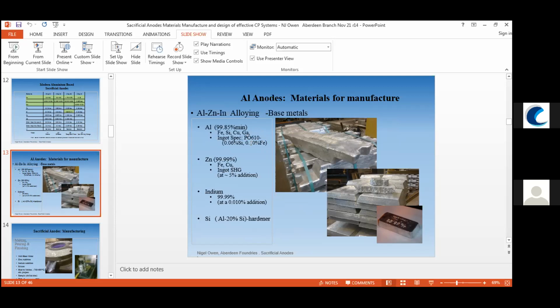We're buying aluminium of P0610 grade, as it's known, and this is a standard grade, and that nomenclature means that you are using 0.06 silicon, and 0.1 iron is the maximum level, and so you will get smelters which run that grade right up to the mark. But you can buy a P0406 grade, as it is known, and then you get 0.04 silicon and 0.06 iron, and that's the premium grade. And you don't go much further than that on offer, unless you're going to superconductors and all sorts of things. You can buy more refined aluminium, and people do that in smaller amounts.